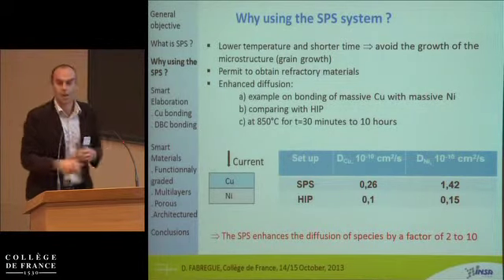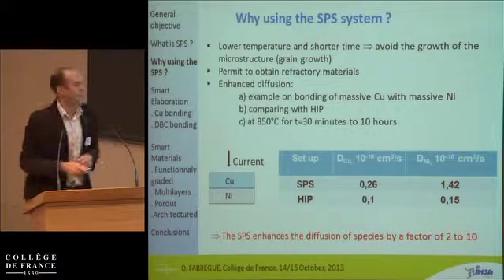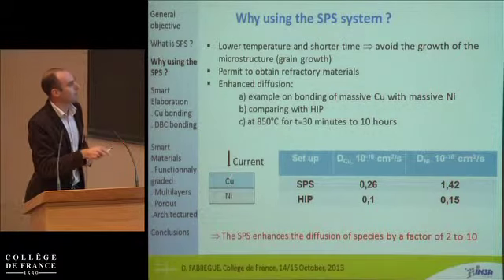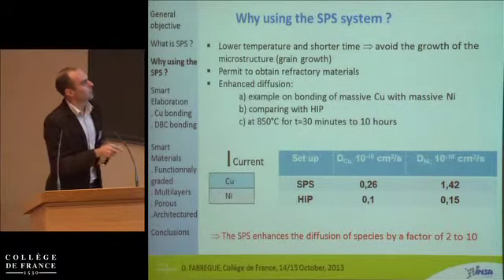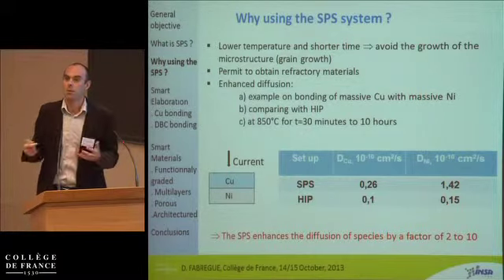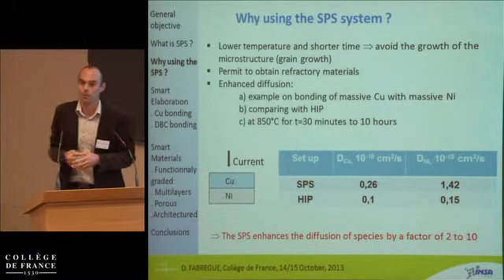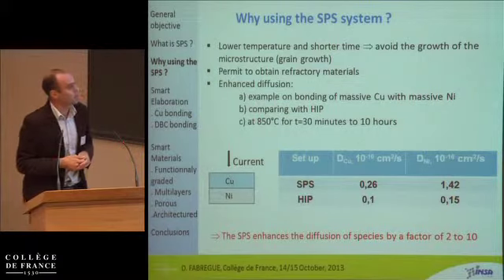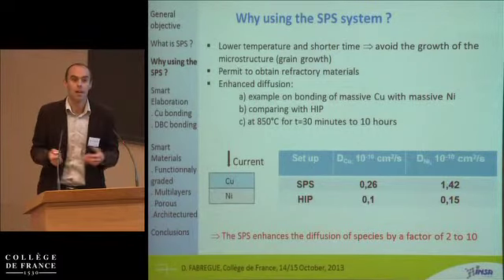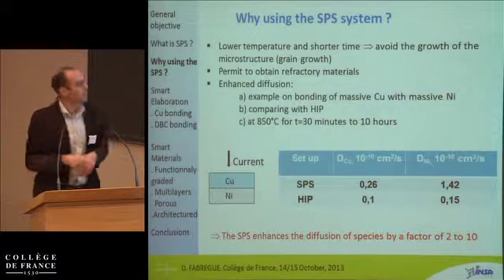So we just make a diffusion couple, as Alexis said to you. We use copper and nickel, and we put that at 850 for 30 minutes to 10 hours. And then you measure the gradient of composition, and then you can calculate the diffusion coefficient in that case.